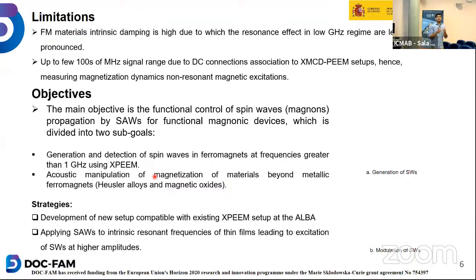With this material, we are dealing with that 500 megahertz already, because it matches the specific frequency of the Alba synchrotron, with which the light circulates. So we are doing that with multiples of that frequency, and we excite the samples up to 500 megahertz because these match. But now we are moving to the gigahertz, because there we will not face this damping problem, and the precession will be greater, the amplitude will be greater, and the propagation of the waves will be greater as well. So that's why we are doing that.